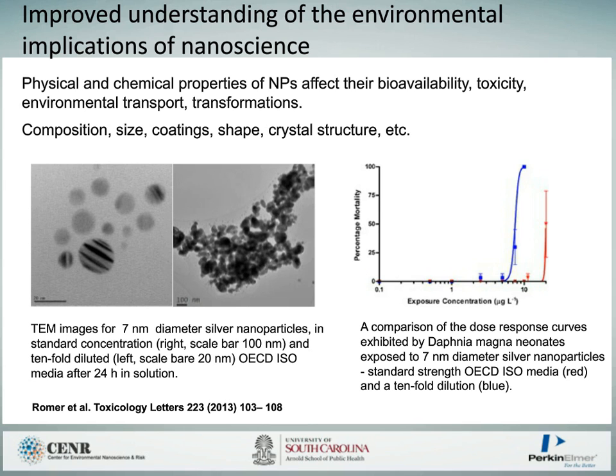To the extent that there are effectively innumerable different types of nanoparticles, if we look at different combinations of all of these physical-chemical properties, we're not dealing with a single material or a single type of material. We're dealing with a whole range of different materials, some of which can be highly toxic and some of which can be non-toxic and inert. An example of that is given here from a publication of ours from 2013, where we synthesized silver nanoparticles and exposed them to Daphnia magna, an invertebrate test model used to understand toxicity. And here we exposed in traditional ISO media, which is a high ionic strength, high salt concentration media, and they aggregated, as in the TEM on the right-hand side.